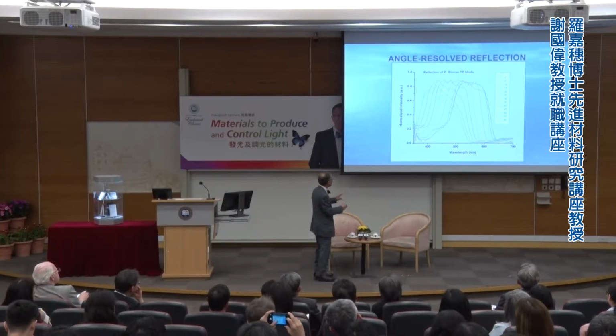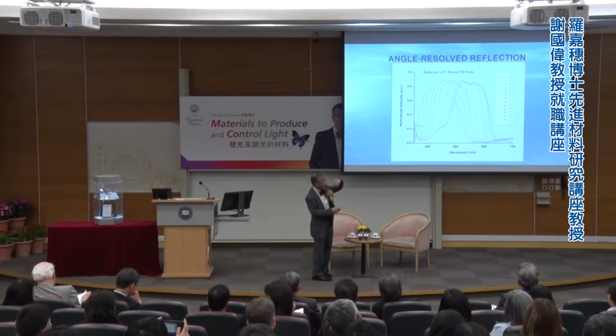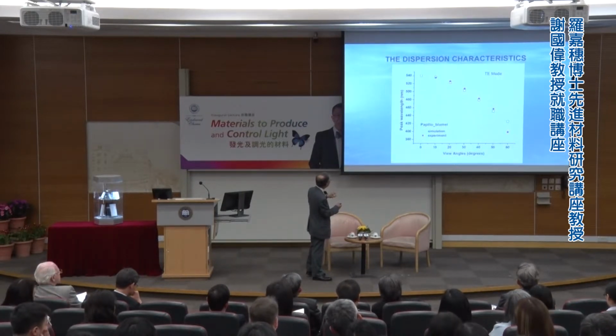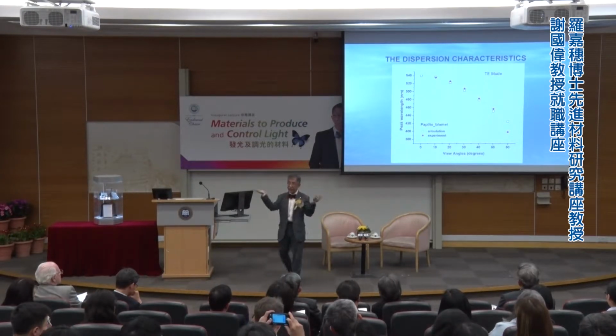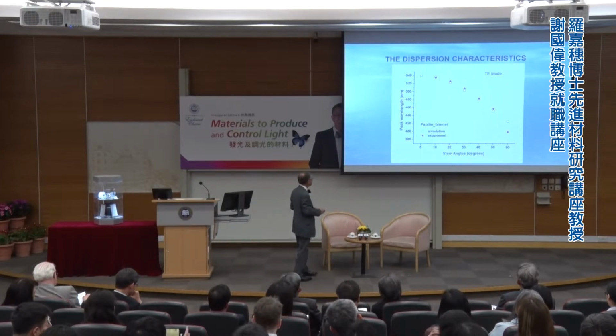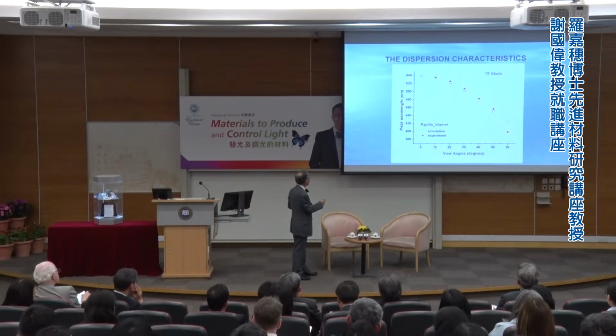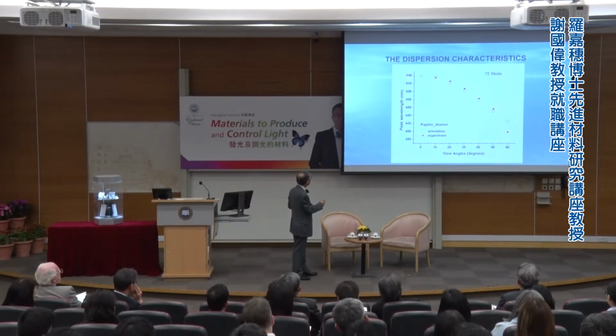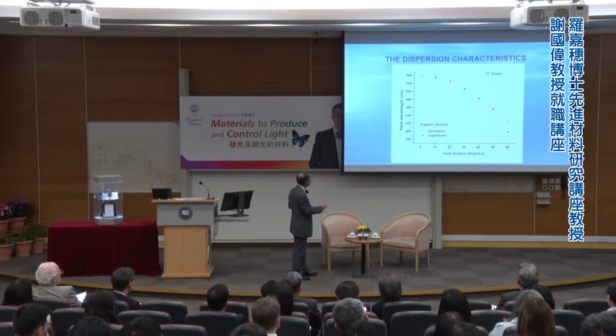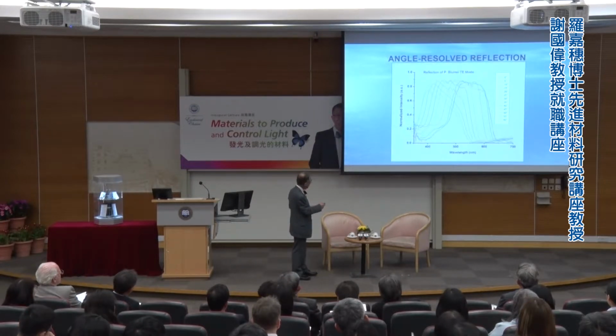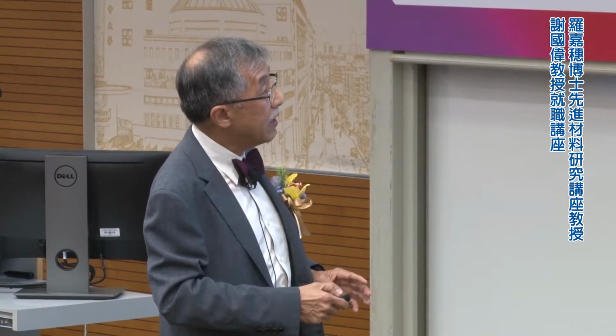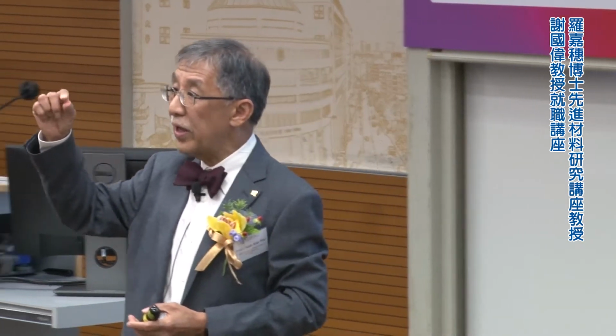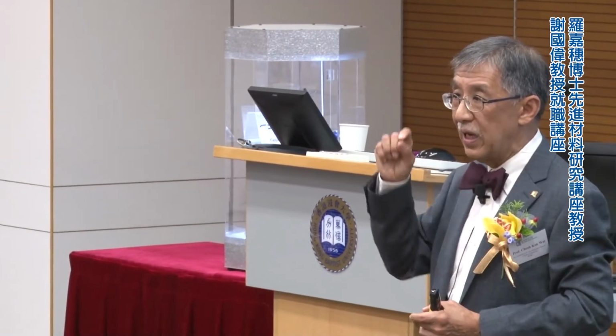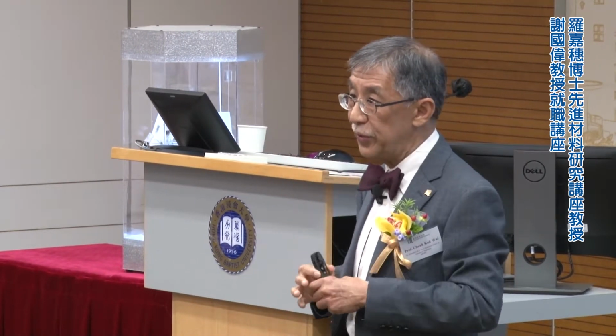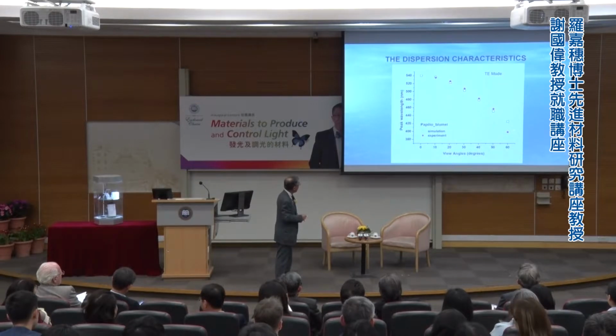And what we have done is looking at the spectrum. I won't go into all the details. We change the angle from shining directly onto it to a glancing angle. And we plot the color as it changes. This is your viewing angle, and this is the wavelength, anything from yellow and green to UV, and that changes with the color. The peak of that is what you see here, and we plot that. The red dot is the experiment. Because we know the solid, we know exactly the organic material's refractive index, and we know what the air is, we put that in, we simulate it, and we have a simulated curve.